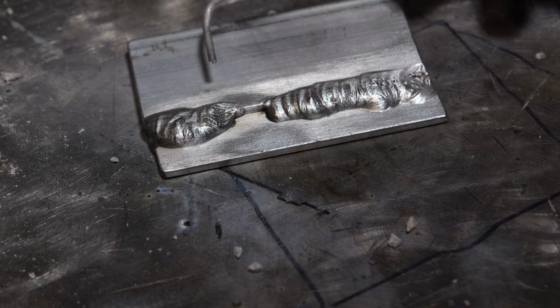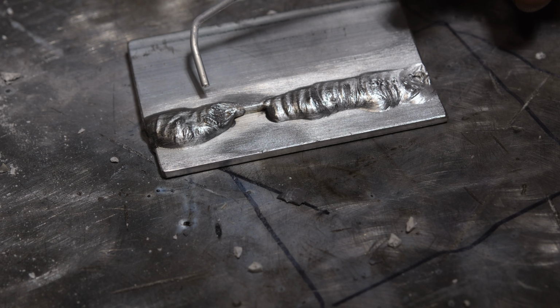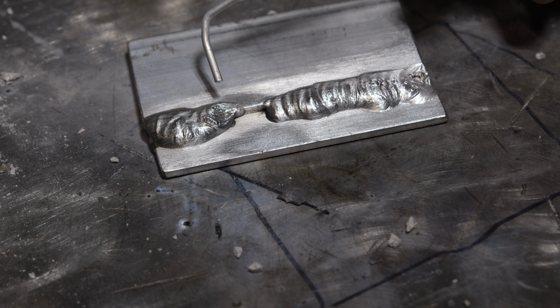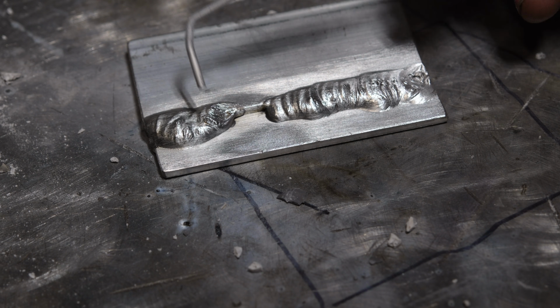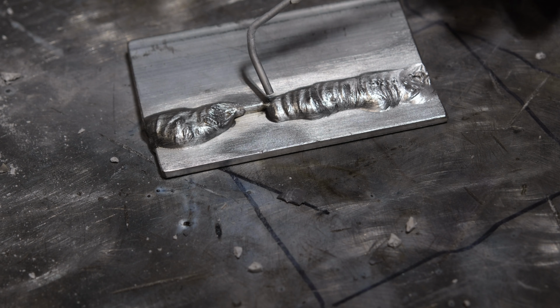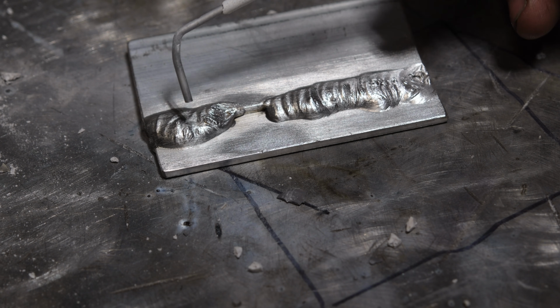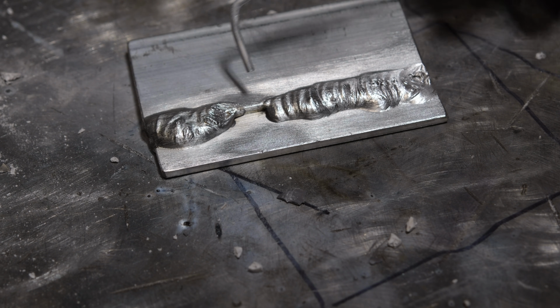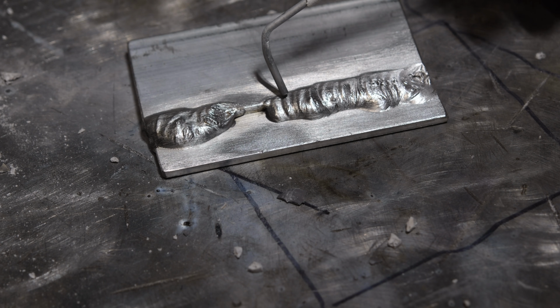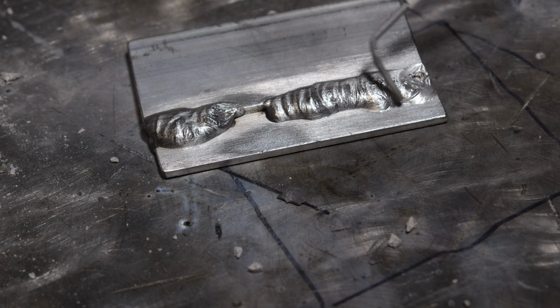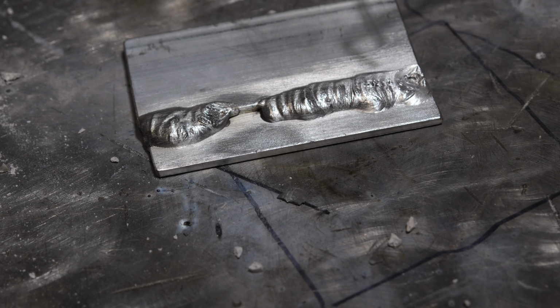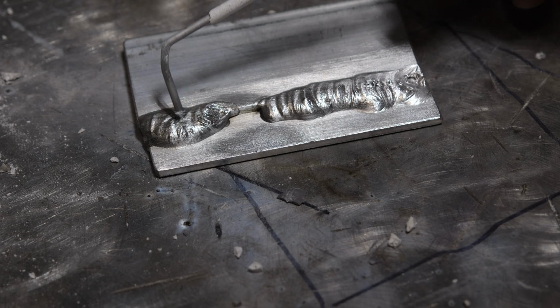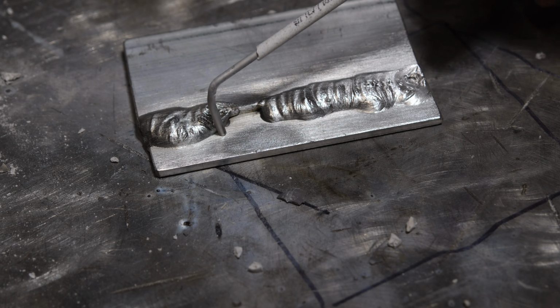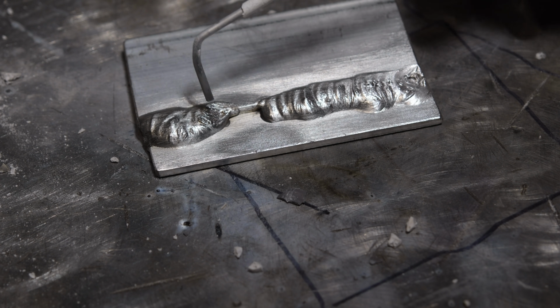So as you probably saw from the arc footage, it's incredibly tough to tell what the hell is actually going on with this stuff. That pond scum oxide layer that exists on top of this aluminum makes it so difficult to see anything. I ended up running probably hotter and more amperage than I really wanted, but at the same time, at least the second, I guess, 2/3 fused and looks reasonably okay. The first, I mean, you can see this cold lap for days, like that's not even fused into anything.